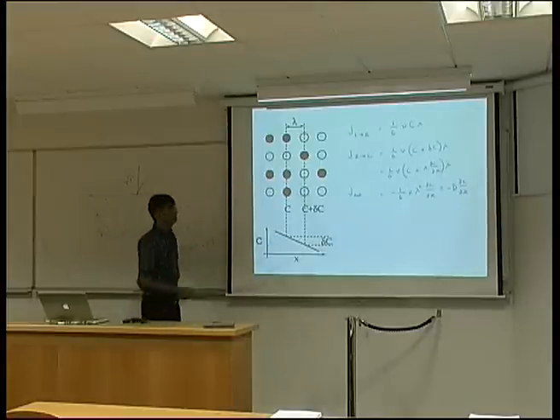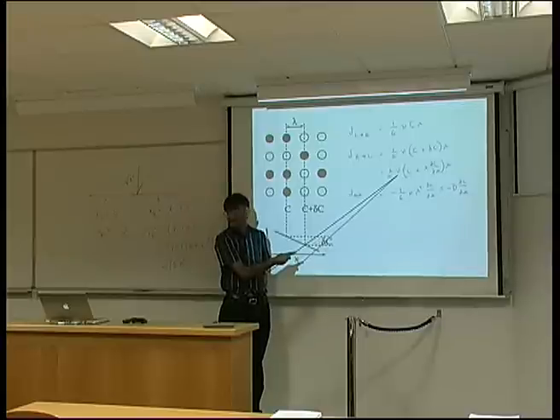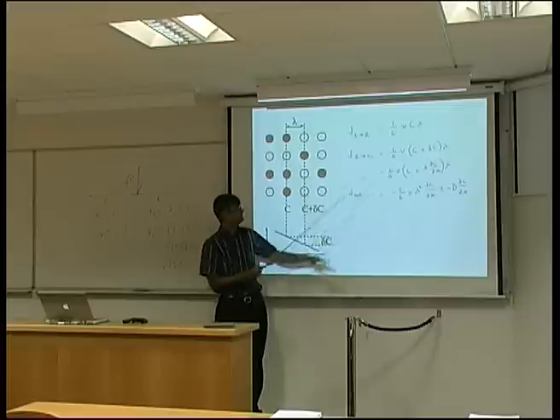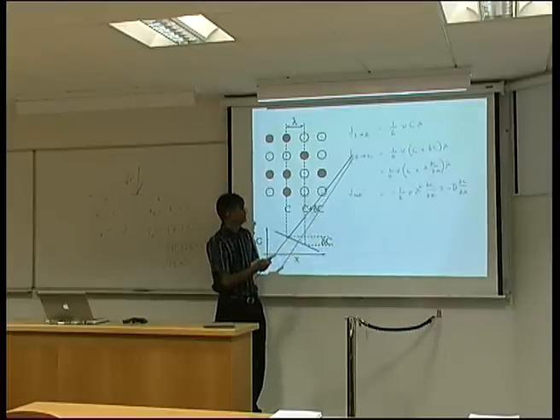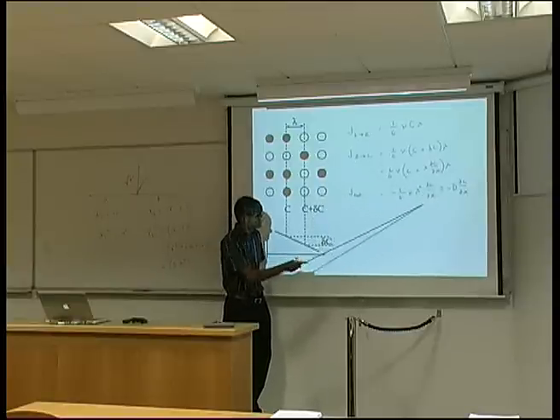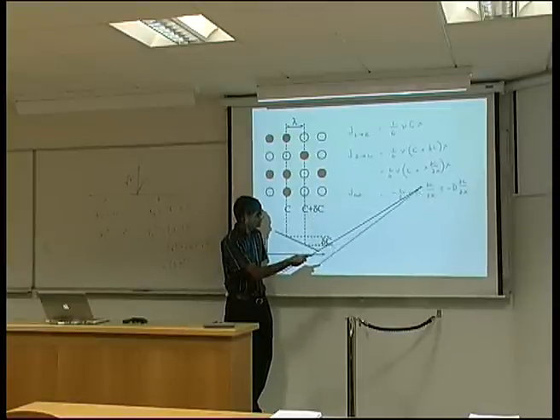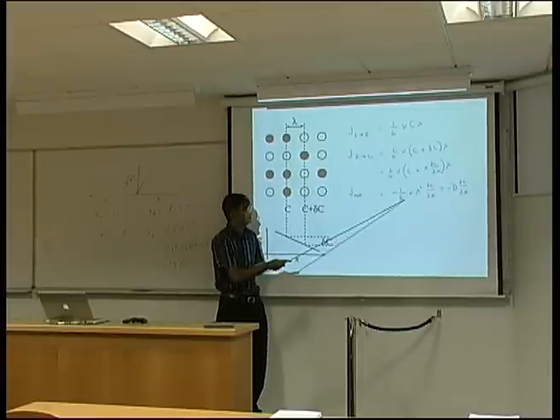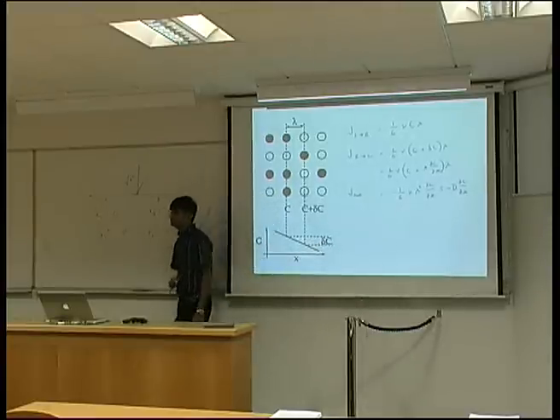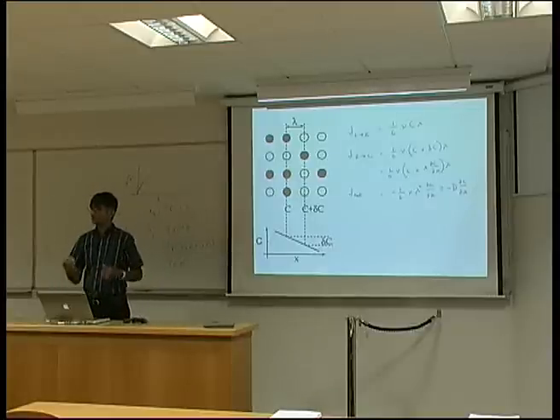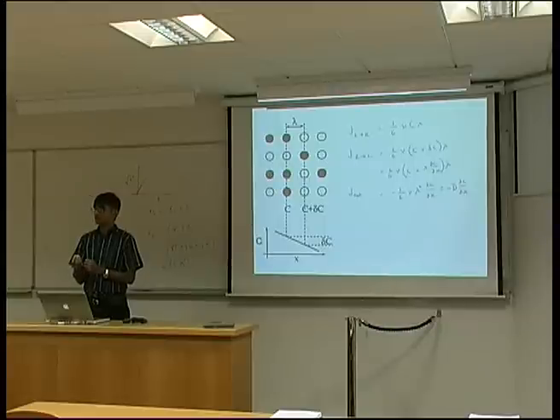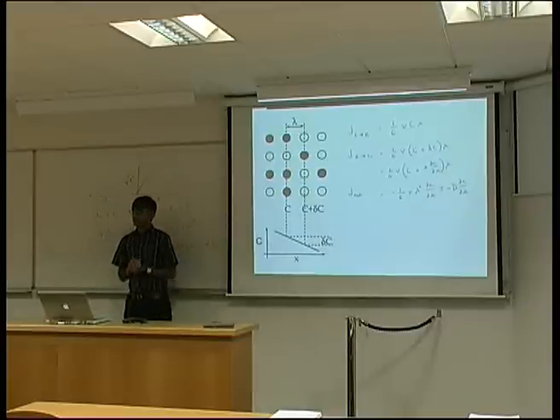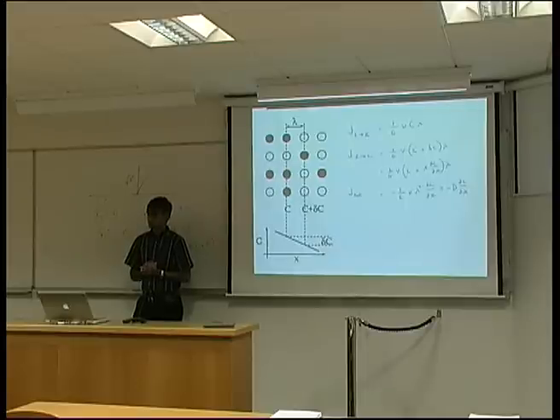Okay, so all we've done is taken the difference between this and this. You want to look at the flux along the x direction, so it's left to right, take away right to left, and that leaves me with just this term here. And we lump all these values, 1/6 nu times lambda squared, as a diffusion coefficient. And this is where Fick's first law of diffusion comes, that the flux along the x direction is minus a diffusion coefficient times the gradient of concentration. Does that make sense? What is the meaning of that minus sign?